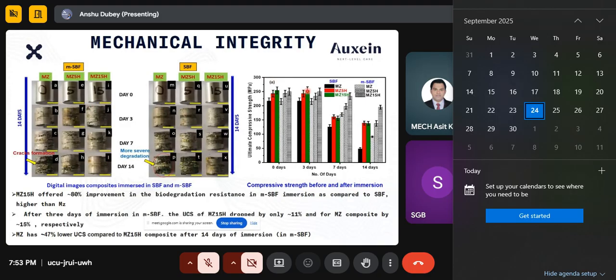If you see, the results are much better in the case of modified simulated body fluid as compared to the simulated body fluid, because it is the most corrosive environment, and the degradation behavior of magnesium takes place in a way that leads to the development of hydrogen gas. So if you see the degradation equation of magnesium, there is always the evolution of hydrogen gas. That is the mechanism involved in the degradation of magnesium.